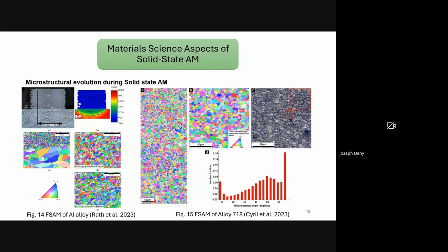In summary, aluminum deposits formed by friction-based additive manufacturing are primarily refined by continuous dynamic recrystallization (CDRX) due to their high stacking fault energy, whereas alloy 718 behaves differently, with microstructural evolution dominated by DDRX, that is discontinuous dynamic recrystallization. The EBSD evidence of fine grains and predominantly high angle boundaries confirms this, and it reflects the characteristic response of a low stacking fault energy alloy under the severe thermomechanical conditions imposed during friction surfacing.